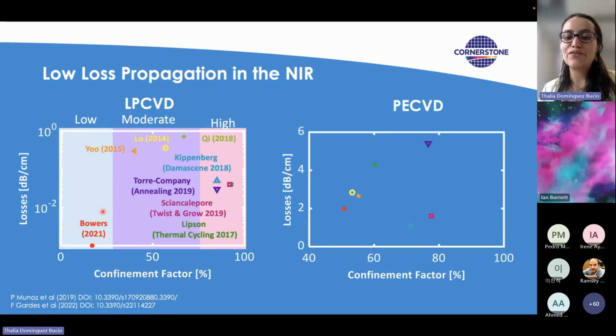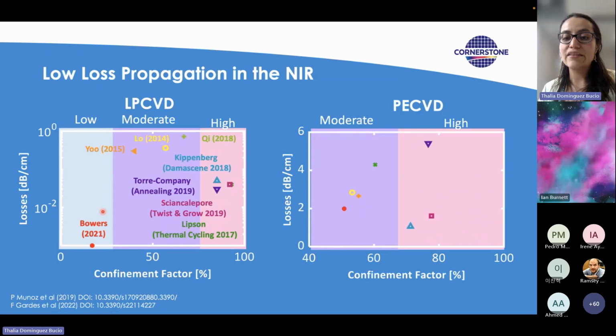Now, if we move to PECVD, the losses look completely different. Now we're talking about losses in the order of, let's say, 1 dB per centimeter all the way to 6 dB per centimeter, give or take, depending on the confinement factor of your waveguide, and on the technique or the recipe you're using to deposit your layers, because they are not at a high temperature. Each of these layers will have more hydrogen content, and that will impact the losses of your waveguide at 1550 nanometers. But give or take, in terms of moderate confinement and high confinement waveguides, you can see losses between 6 dB per centimeter and 2 dB per centimeter, which in some cases, if we're talking about 2 dB per centimeter, might be better than the losses that you can achieve with silicon.